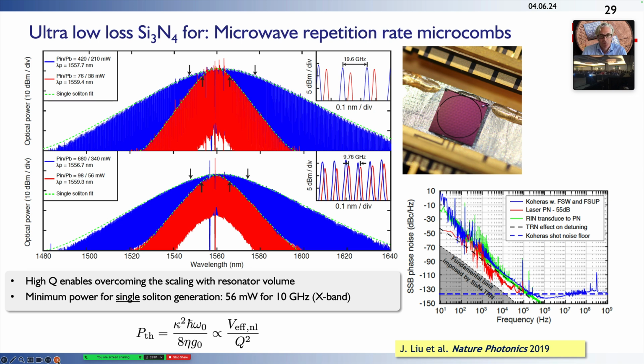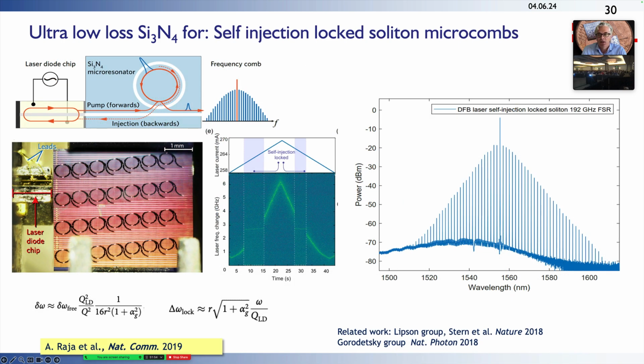Now, due to the low threshold, you can also integrate these devices directly with semiconductor gain media. Here what is shown is a 100 milliwatt indium phosphide DFB that's directly butt coupled to a silicon nitride waveguide and resonator. And here you have two effects happening. The first is self-injection locking, whereby a portion of the light is back reflected into the DFB and creates a locking effect. This purifies the spectral tone. I'll say something about this in a bit, and creates very narrow linewidth lasers.